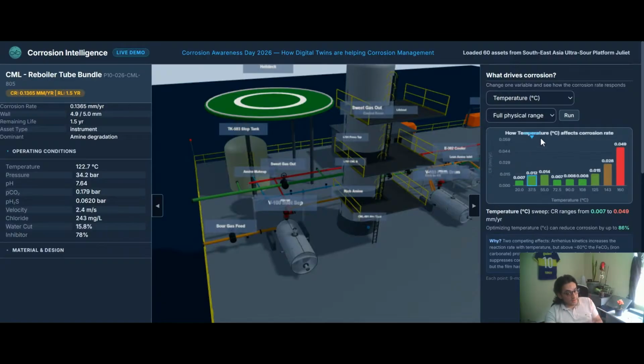But for an asset that we don't have that compelling information between the physics informed machine learning and the calculating mechanical equations, we don't have the curve. So that tells you that the linear curves are not following all the physics laws. It's only going as a logical way to see if the temperature increases. It doesn't matter if we have this protected layer between this temperature creating because of the electrochemistry reaction inside the pipe. No, it just tells you increasing the temperature, increasing the corrosion rate. So no sweet spot to reducing or increasing the corrosion rate between the range of the temperature operation.